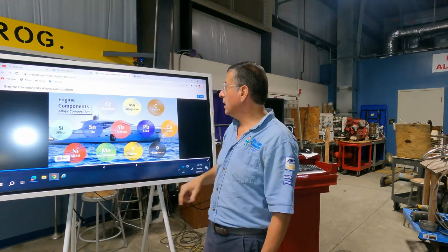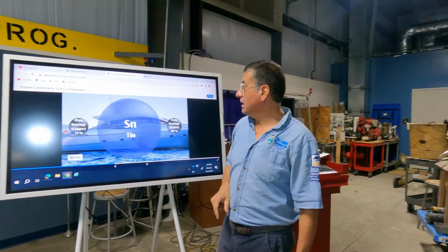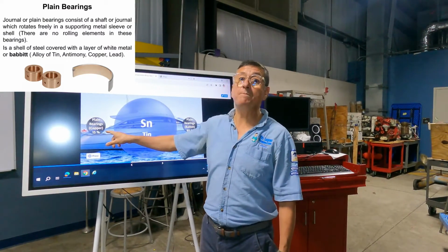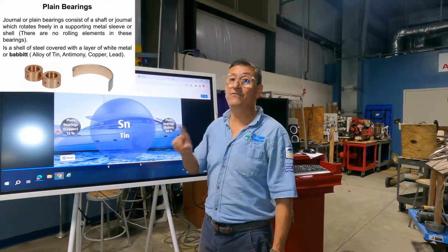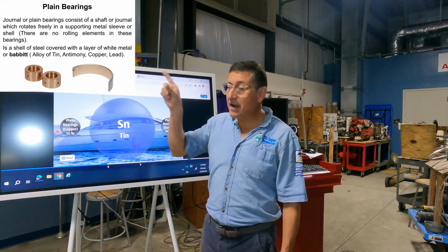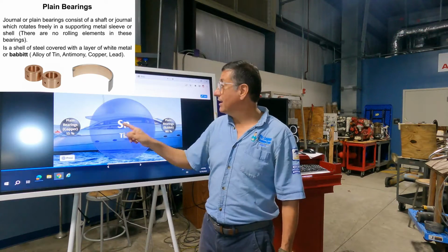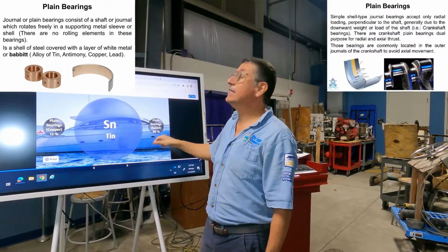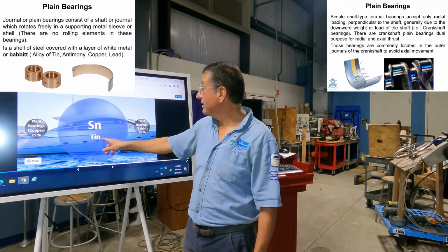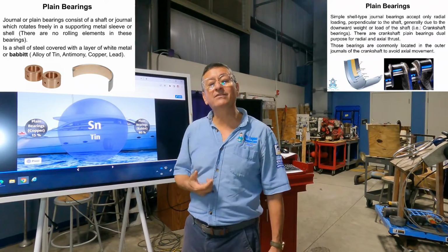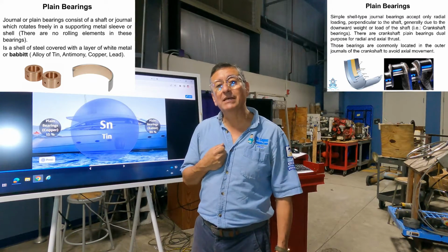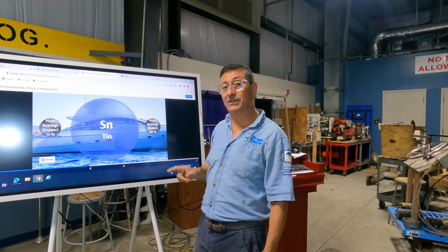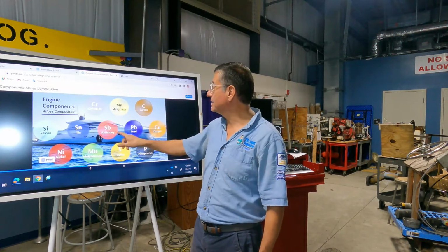Another metal dispersed in the oil sample that I recommend you pay attention to when you receive the report is tin. Tin on the plain bearings, if the plain bearings are in copper, 15%. Wow, 15% of those copper bearings is tin, and 80% in the plain bearings if the plain bearings are babbitted. Tin. Oh wow, this is very important. We are going to analyze that metal in detail.